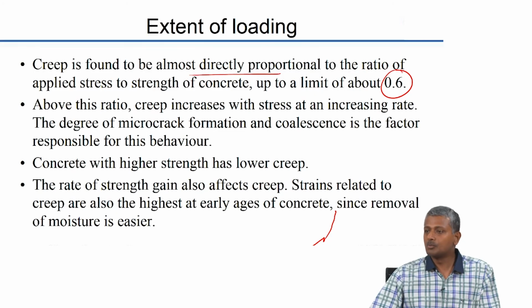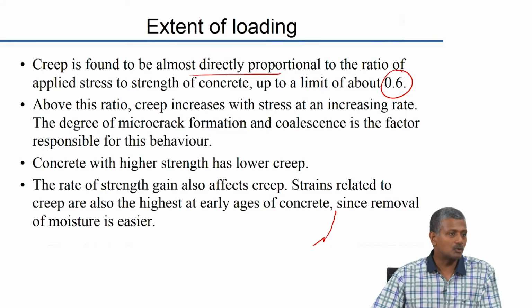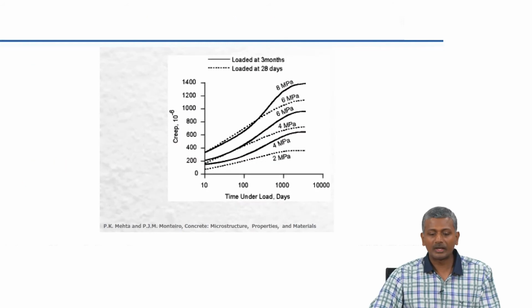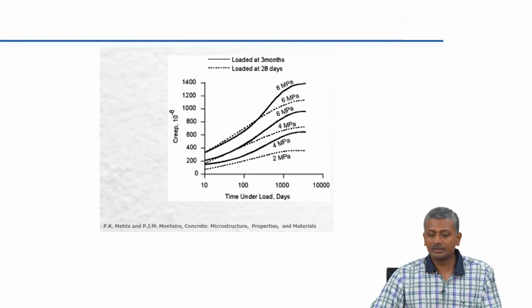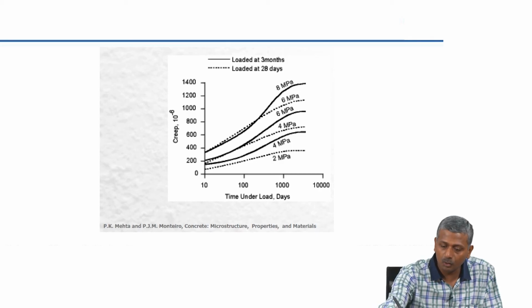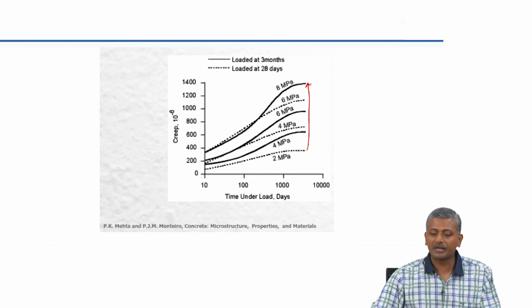At early ages there is more water available to move around. At later ages this water would have completely got used up in the system. Again, this is showing you the creep with time for different levels of load in the material. So, as the loading goes from 2 megapascals to 8 megapascals, your creep can increase by a factor of nearly 6 times. That's a huge level of increase.